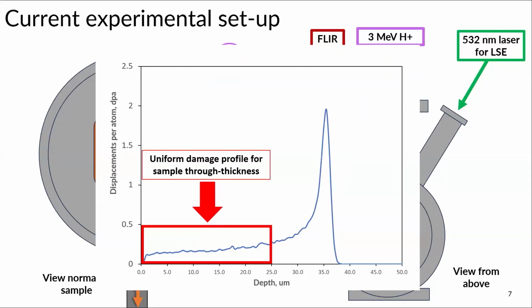And the reason I use 3 MeV protons and also super thin samples is that we want a uniform damage profile through the thickness of my sample. In order to achieve that, you can do that when you have 25 microns, at least less than 35 microns thick. So it's incredibly challenging to work with, because that's like a quarter of the thickness of a human hair.